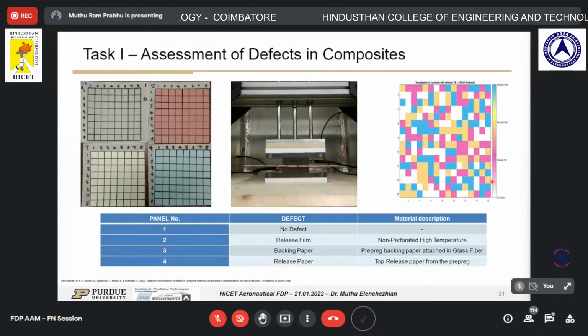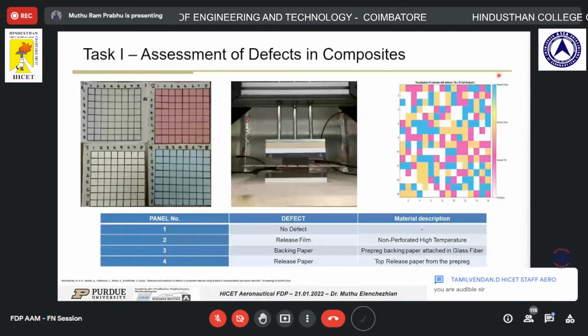So the first research task was performed to actually assess the defects in composite materials. I made 4 different composite panels and artificially induced defects in them, like using a release film, using backing paper, and using release paper. Based on this, we actually did the broadband dielectric spectroscopy measurements. If you imagine what the actual panel manufactured will look like, it will look like these different images with different defects in them completely.